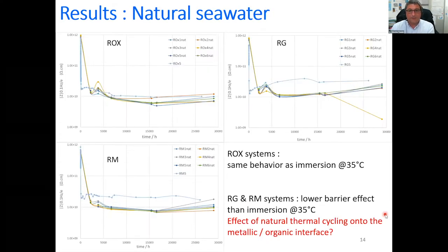Now, these are the results for the panels that were immersed in natural seawater, and they are compared to a typical curve, which is in blue here, that was obtained during the immersion at 35 degrees C in lab. As you can see, for the ROX system, we've got quite similar value. But for RM and RG, the value obtained here for the immersion in natural seawater seem to be quite lower than those observed with the immersion at 35. Of course, we can think about the effect of temperature, because we know that in natural condition we have temperature variation and maybe so an effect of the natural thermal cycling onto the metallic organic interface for the RM and RG systems.